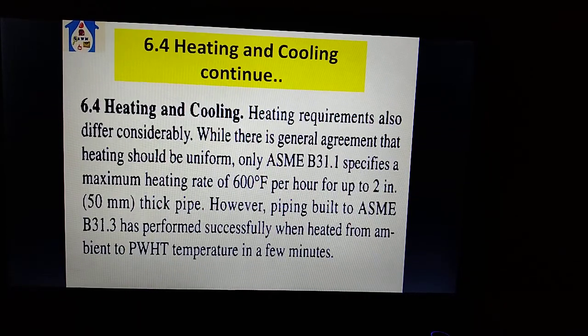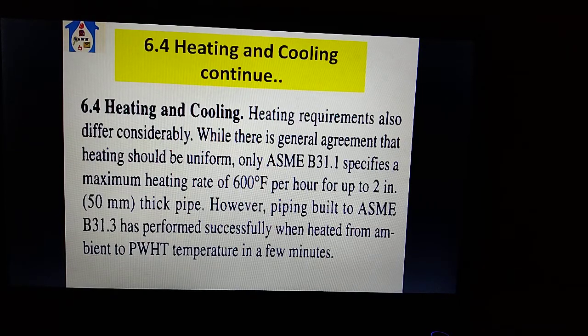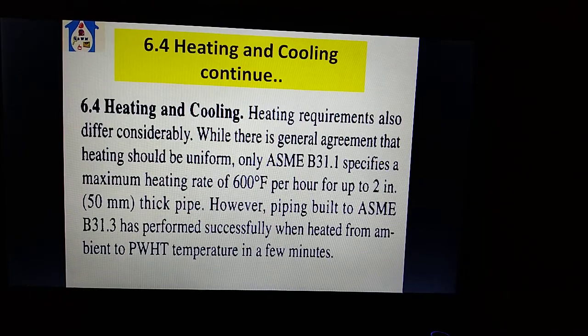Heating and cooling, continued. Heating and cooling requirements also differ considerably, while there is generally agreement that heating should be uniform. Only ASME B31.1 specifies a maximum heating rate of 600 degrees Fahrenheit per hour for up to 2 inch, 50 mm thick pipe. However, pipe built to ASME B31.3 has performed successfully when heated from ambient to PWHT temperature in a few minutes.